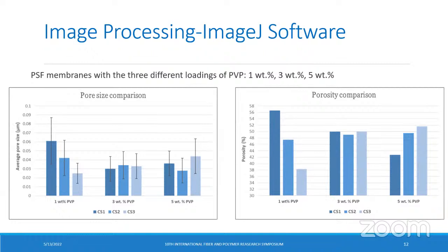Here we have done some comparison for the 3 different loadings in terms of the pore size and in terms of porosity. Now, although they are all within standard deviation, we can clearly see that there is more variation for the 1 weight% and 5 weight% of PVP, whereas the 3 weight% gives us more consistent values for the 3 different randomly selected samples. And therefore we have come to the conclusion that this particular loading gives us a more homogeneous microstructure, which we will also later be using because we are working on some reinforcement with cellulose nanofiber.